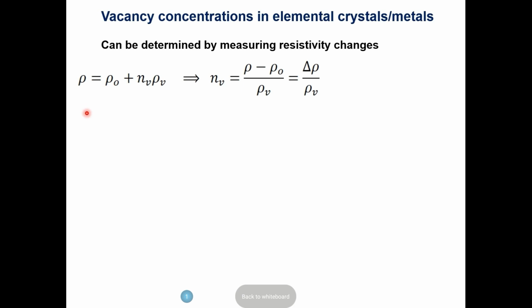So you model the electrical resistivity without any defect, which comes from the data, plus you introduce a number of defects, each associated with some electrical resistivity, which is the defect part. Then you can rearrange the number of defects, which can be expressed as delta rho, the change of resistivity, divided by the resistivity introduced by each defect, as a normalization.